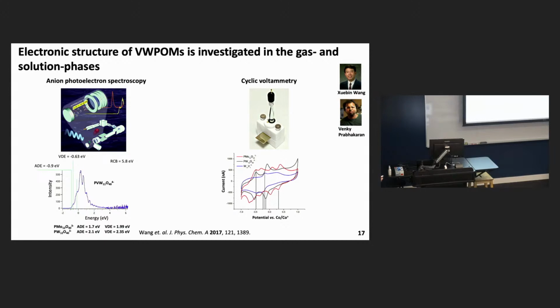In solution, what we can do is soft land that species onto an electrode surface, which we can then assemble into an electrochemical cell as shown here. We can make the same sort of cyclic voltammetry measurements as I showed you before, but now we have the purple species, which contains a single vanadium atom. You can see the dramatic effect on the redox properties of that cluster as a result of a single vanadium substitution.